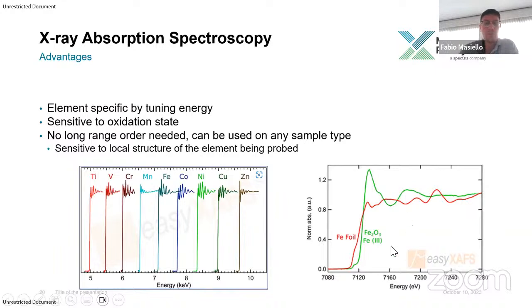For example, you can recognize the difference between iron oxide Fe2O3 and simple iron foil. Also, in this case, it doesn't need long range order like total scattering. It can be used on any sample type, and it is sensitive to the local structure of the element being probed.